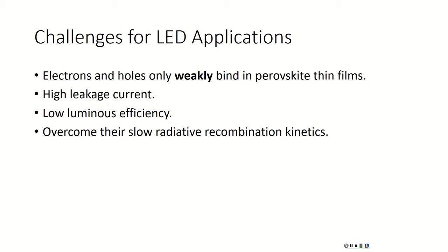That goes back to, well, current materials don't have the highest external quantum efficiencies. The recent paper that I'll be talking about later has an external quantum efficiency of 14.3%. So 14% is not impressive by any means, but it is comparable to conventional LEDs on the market. So that's what I mean by low luminous efficiency. It's not high, but it's working.